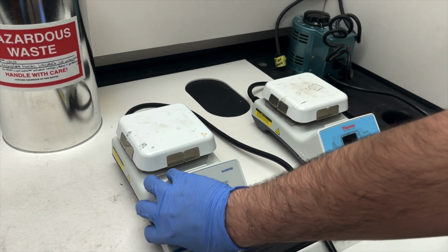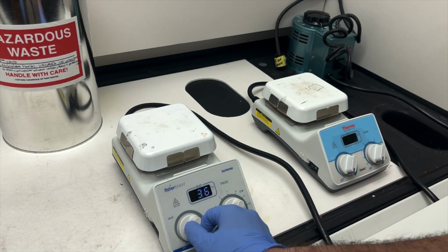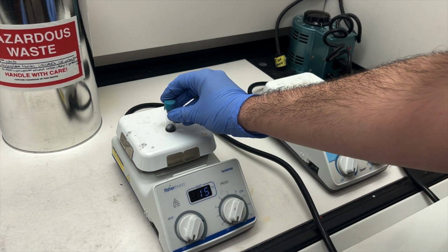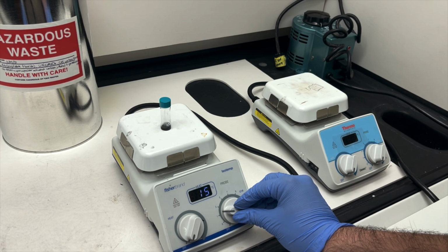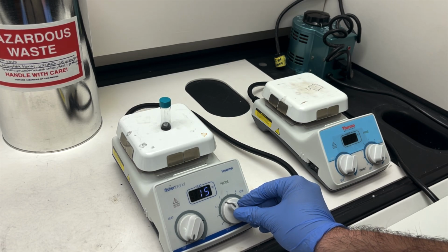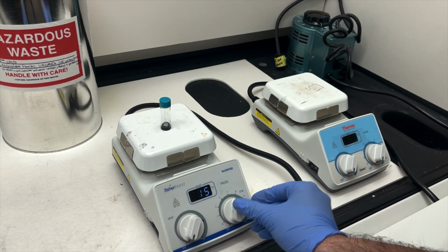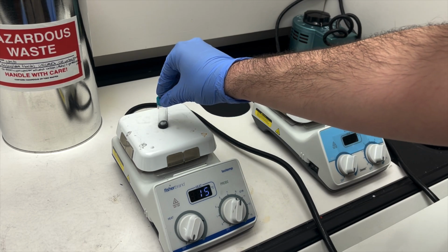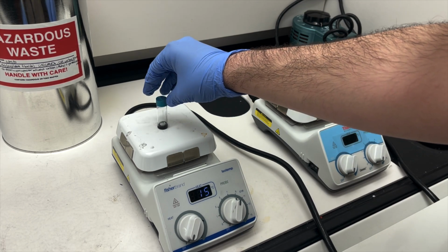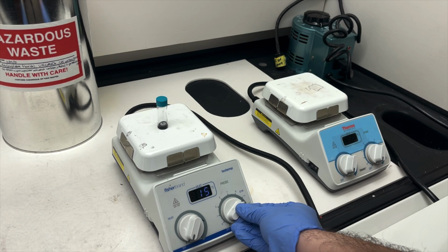The hot plates are equipped with both heat elements and magnetic stirring, the latter of which can be controlled with the knob on the right. Setting our slurry onto the hot plate and turning on the magnetic stirring, we will allow this to sit and stir for 10 minutes before moving on to the next step.